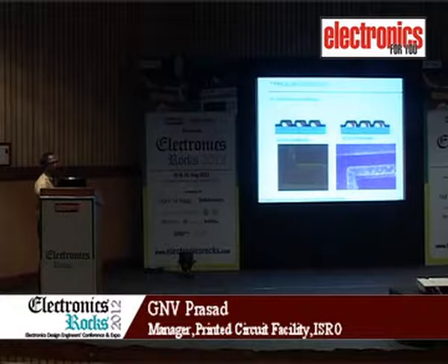Then we have to see adhesion of the solder mask. It should have a full coverage of the traces, so that is a good adhesion what we are showing. And if you see between the trace and the solder mask cover, you find a gap. This gap is dangerous because it can accumulate lot of contamination during the assembly process and can lead to the failure.